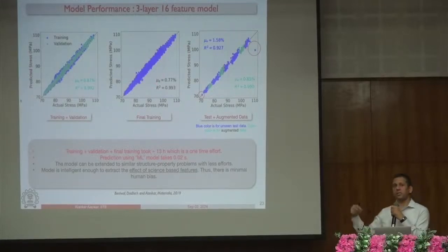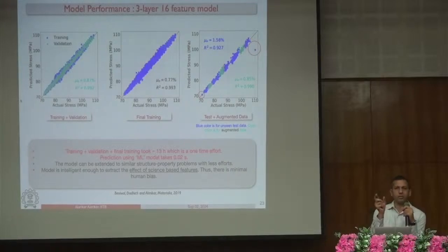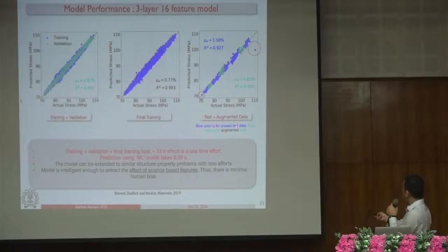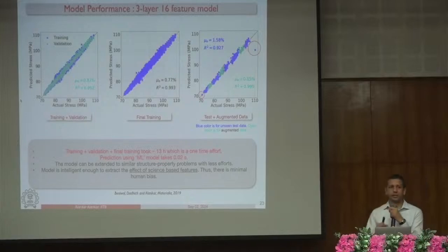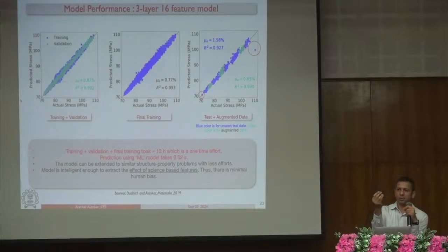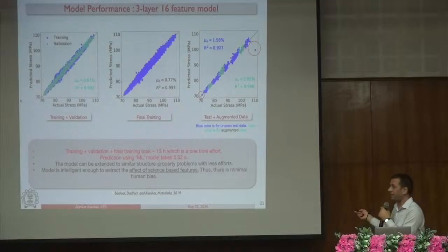In this case, we ran some additional simulations, fresh simulations, which were not seen by the model at all. So this data, blue color is the unseen data, right? And the cyan color is the augmented data, meaning if you have a microstructure, if you flip it by 180 degrees, it is the same microstructure. If you do the tensile test like this or like this, the property will not change. By using those physical rules, we did some of the augmented data generation, and it was able to do pretty nice. Just for curiosity, we also used some additional data which was not part of the training.